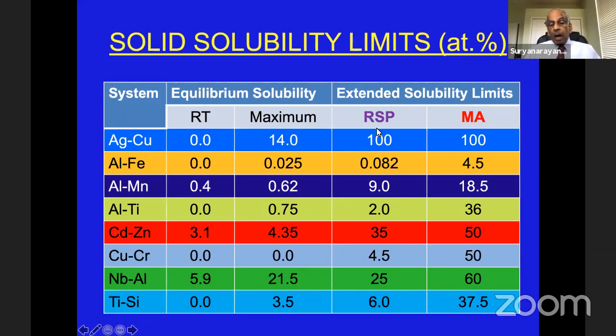But the difference between RSP and MA is by mechanical alloying, you're able to increase the solubility to a much higher level than what is possible by RSP methods. You can see, for example, 9%, 18%, 2%, 36%, 4.5%, 50%, 6%, 37.5%, like that. But I also should confess here, there are certain cases where you are not able to increase the solubility either by RSP or MA to a large extent. To a limited extent, yes, but not to a very large extent like this.